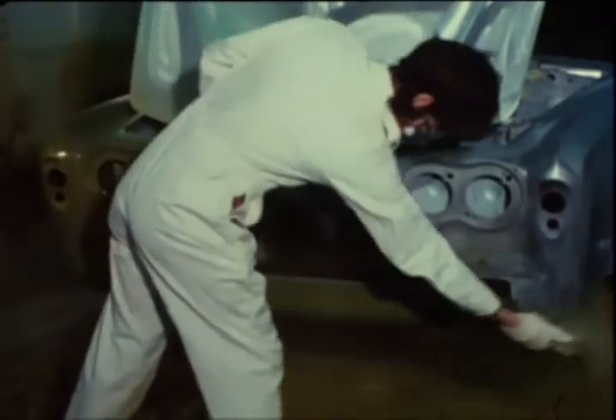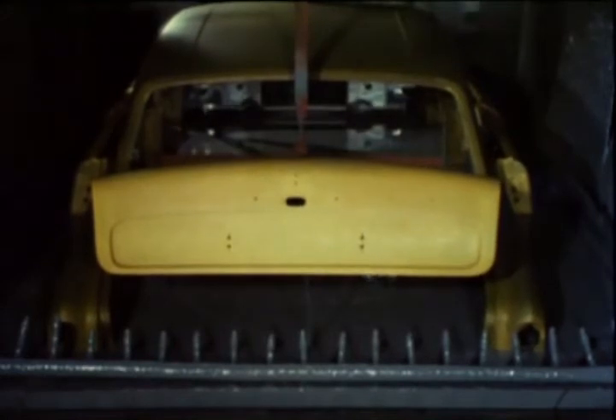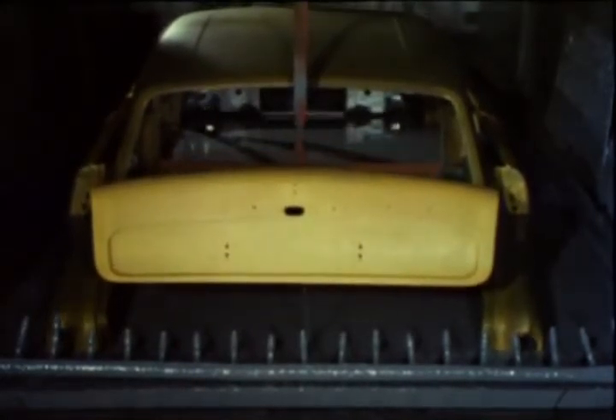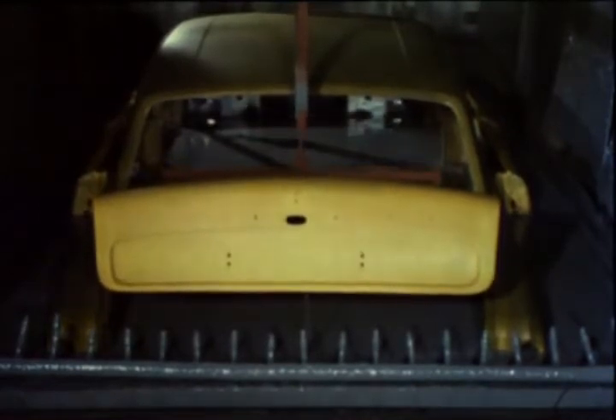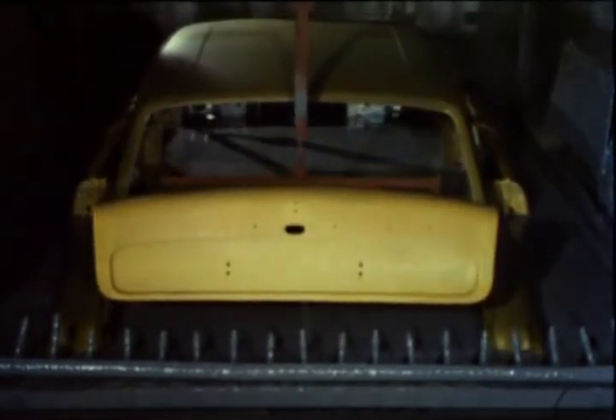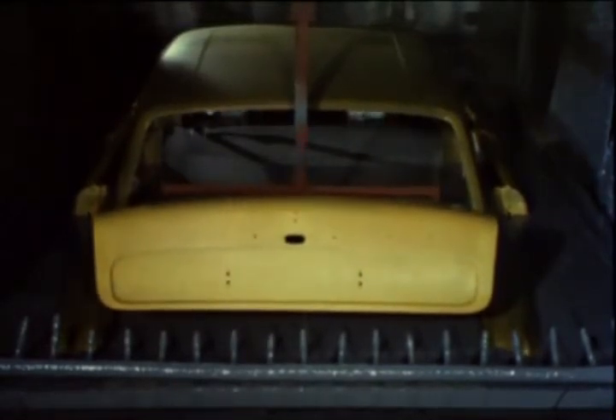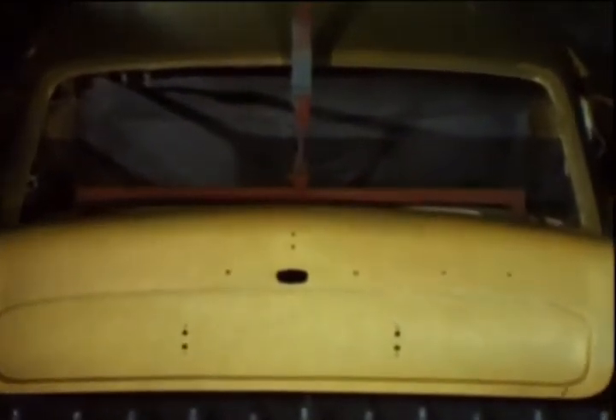Because it is used in extreme conditions, avoiding corrosion in the car is neither easy nor cheap, but it can be done if cost is not all important. The body has been phosphate coated to improve adhesion and then washed. After drying, it's coated with a primer, which carries zinc chromate to control corrosion. Each body is completely immersed in a further waterborne primer. Some processes use electrophoresis to improve the paint distribution. This primer provides a good base for the more resistant coatings to follow. It's dried in a heated oven.